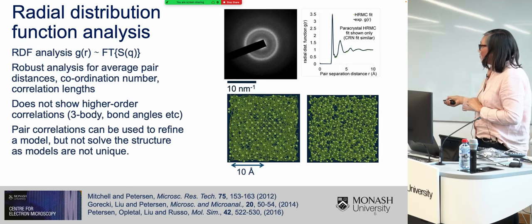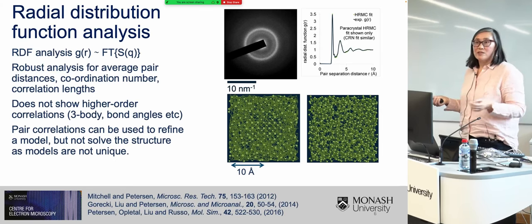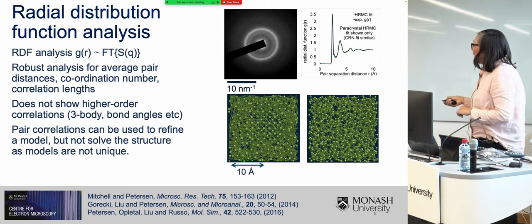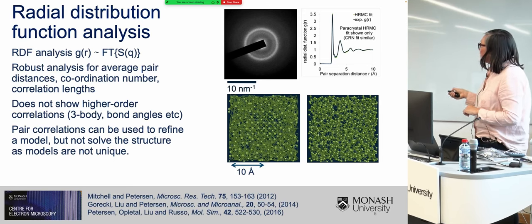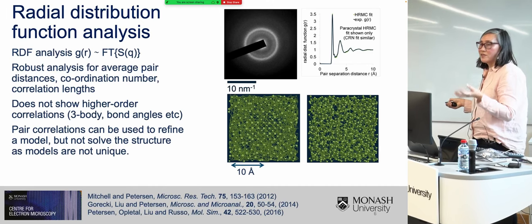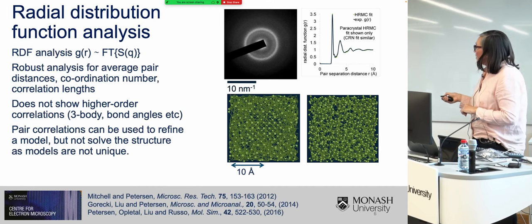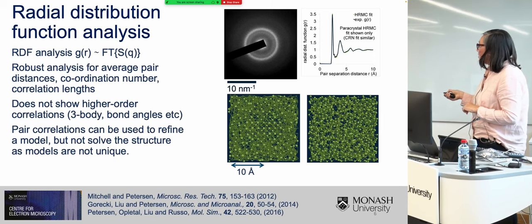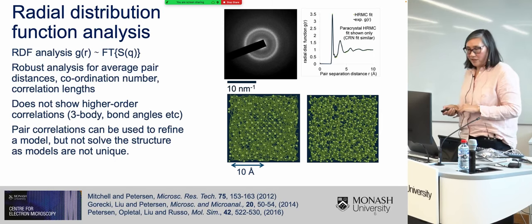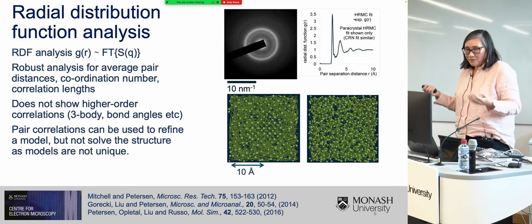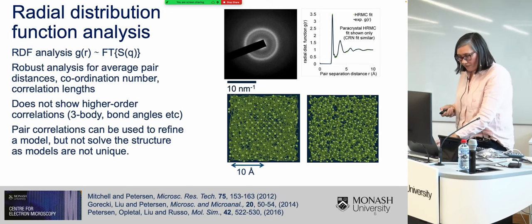And this is what Tim Petersen has done in these very nice models down here that he prepared using reverse Monte Carlo. Both of these models fit this radial distribution function equally well, but you can see that they are not unique, and that's the problem with this approach. So here, a nanocrystal has actually nucleated, whereas here you're just getting a continuous random network. And so evidently we need some new approaches.